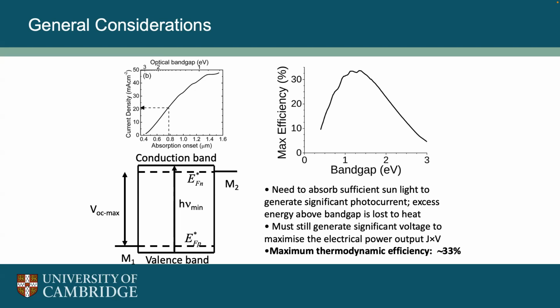And even if there's traps there, because you've got very high carrier densities, you can saturate those traps. So it's quite a complicated mechanism, but we're starting to get a handle on it. The other thing is this funneling allows carriers to move away from where the traps are. The funneling actually draws carriers to other regions where there aren't traps. So it's mostly the chemical heterogeneity, I would say, but it's complicated and hard to harness and to make sure there's a gain, or at least to maximize the gain.